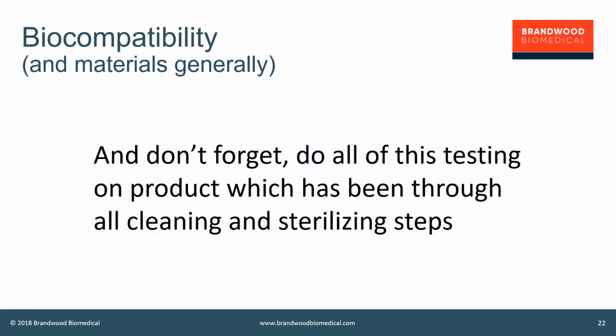And don't forget to do all of this testing on product which has been through the cleaning and sterilizing steps. So often manufacturers make the mistake, particularly when coming to this for the first time, of testing samples which have been straight off the printer, but not been cleaned and not been sterilized, and the testing on those non-clean, non-sterilized samples is not valid because it doesn't represent what may be added to the device in the cleaning and sterilizing steps, or what may be taken away in the cleaning step.